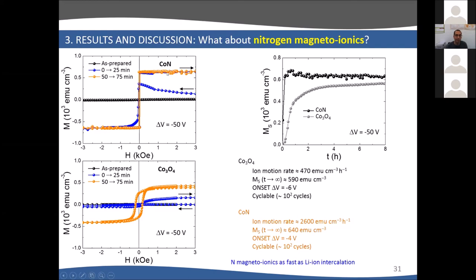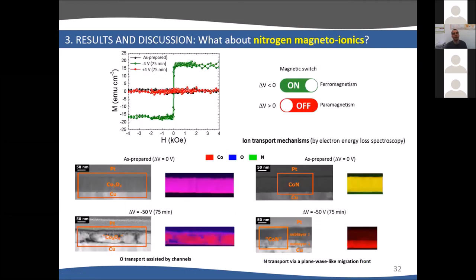The second loop is already closed and horizontal. For cobalt oxide, the increase is much less pronounced in the first loop. This is shown on the right. For cobalt nitride, the increase of saturation magnetization is faster, it reaches a larger value. Also interesting is that the onset for cobalt oxide was minus 6 volts, for cobalt nitride it's minus 4 volts. This works a bit better than for cobalt oxide.